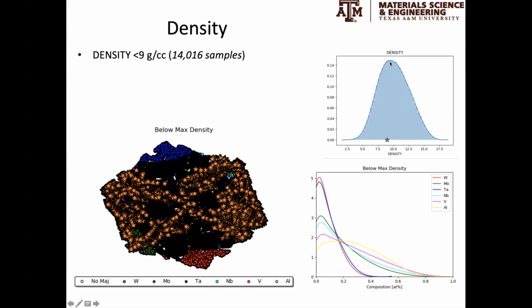This is the distribution of densities in the alloy space that we find. So there are some really low density alloys, and we also have our target. So less than half of the alloys actually satisfy the 9 grams per cubic centimeter target.